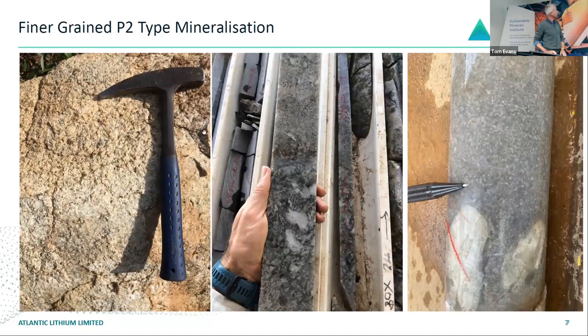And then this is what the finer grained P2 mineralization looks like here in outcrop. When we first saw it in mapping, back in 2016, we didn't have any experience in pegmatite exploration. We were actually working on gold projects, and we thought these were all granites. But when you took a closer look, you could see all these little blue crystals here. They're apatite crystals. And when we sampled it and the assays came back, it's exactly the same grade as the coarse grain spodumene pegmatite, but just very much finer grained.